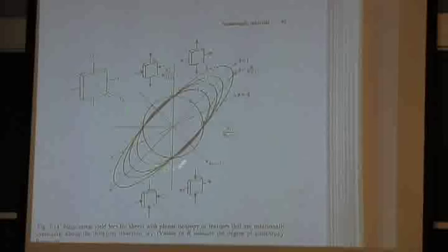Anyway, so if you take sheet material and you pull it biaxially, here's our yield locus, with an isotropy of 1, that's your isotropic von Mises ellipse. With an R value of 0, you end up with a circle. And with an R value of 2, 3, or 5, you can get these long major axis ellipses. And there's something called a beta value. We won't go into that. It's just a variation. You can look in Backofen if you want to see what beta is. It's just another variation on things. Well, how do you get anisotropic behavior?